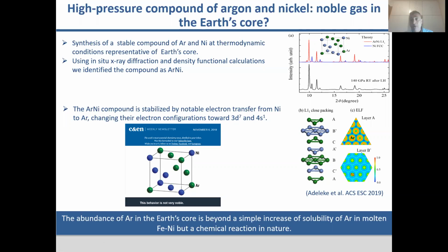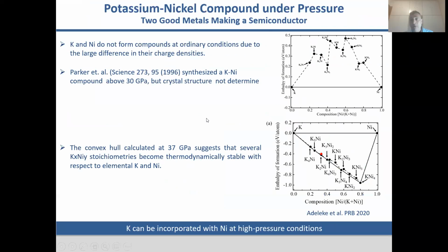I don't see the chat, so if there are questions, I will try to respond at the end. We turned our attention towards potassium and nickel, trying to understand what kind of compounds can form. At ambient conditions, as you may see in the convex hull here, there are no stable compounds. In reality, there is no convex hull, to be exact. The main reason is the large difference in their charge densities, and this kind of explanation applies also to the case of iron.